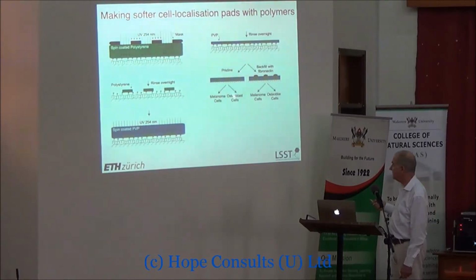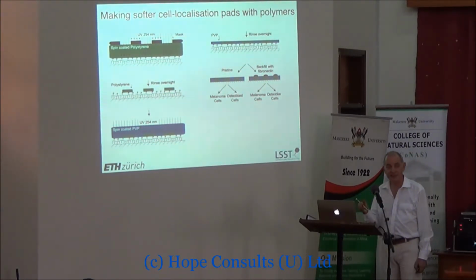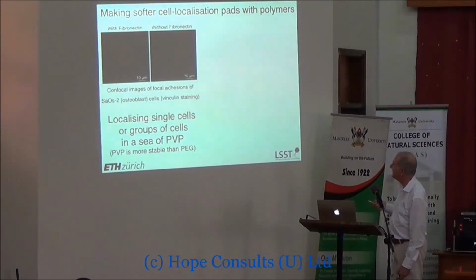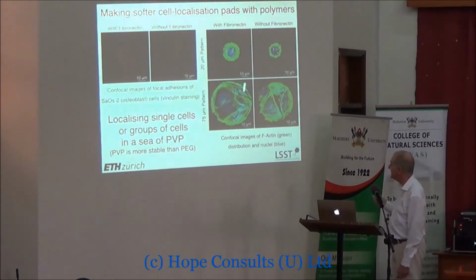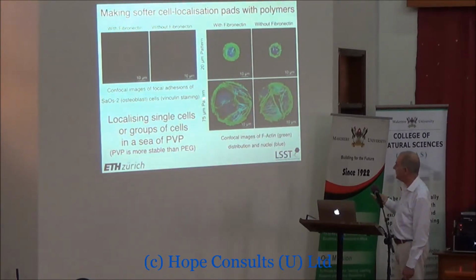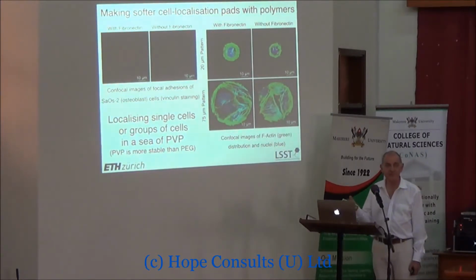We expose it either directly to different cells in serum, or first of all we coat it with a particular protein that we know facilitates cell adhesion, and then we expose it to the cells. And here you can't see terribly well. This you can see better. Let's just look at this side. So here we've taken two different sizes of patterns. One is 20 micrometers, one's 75 micrometers, and we've exposed it to osteoblasts, which are bone cells, and then we've stained it with things that stain different components of the cell. So the blue is the cell nucleus, and the green is the mechanism that the cell uses for sticking to the surface. And here you can see we've managed to isolate a single cell on the surface, and with the bigger pattern we have multiple cells.